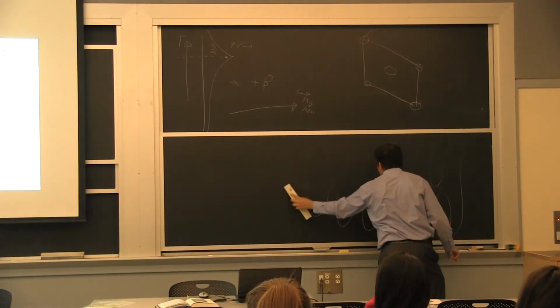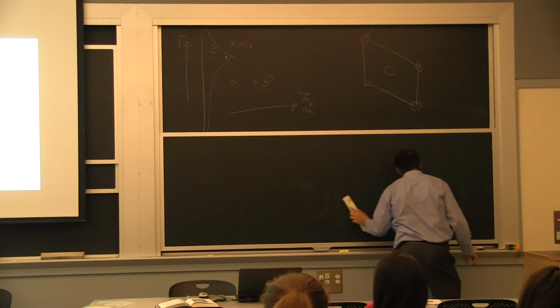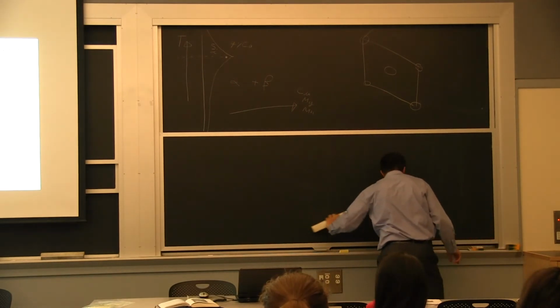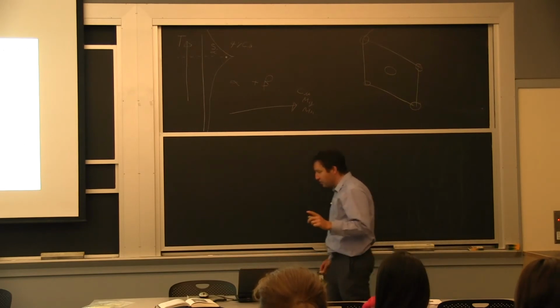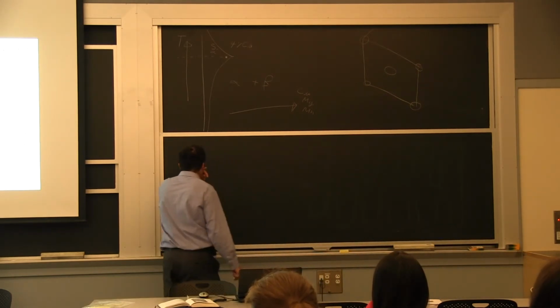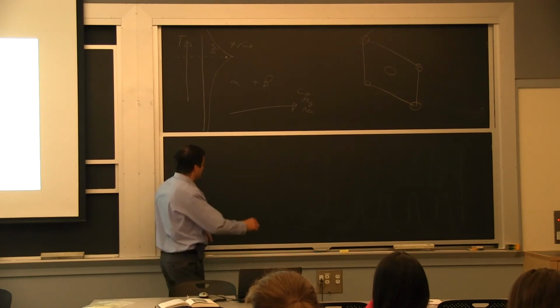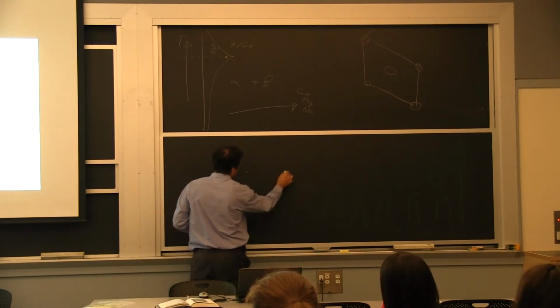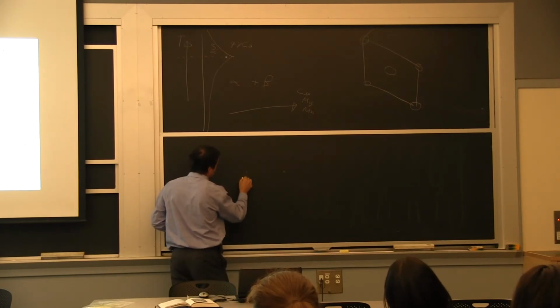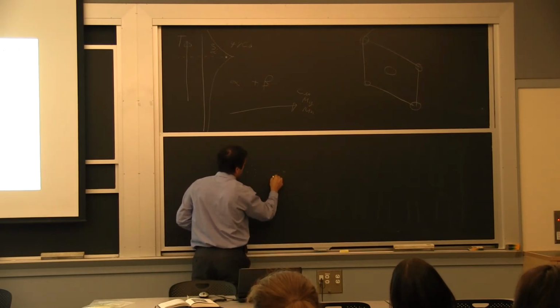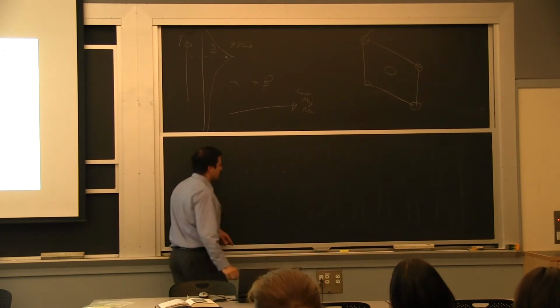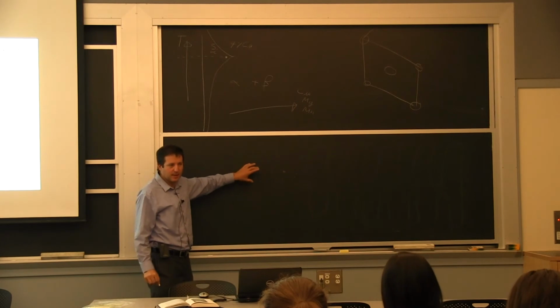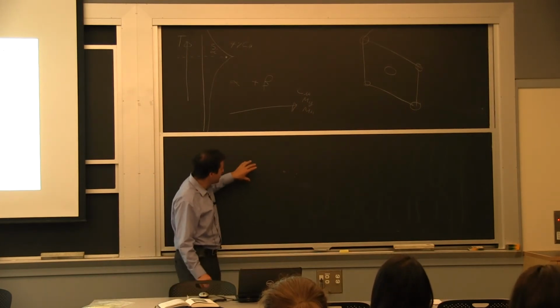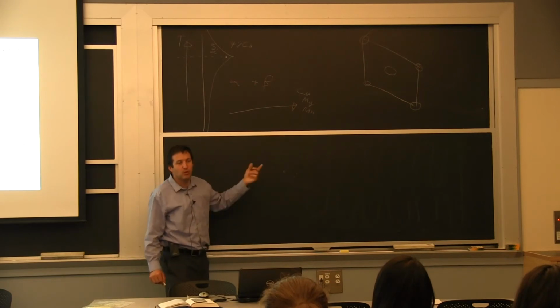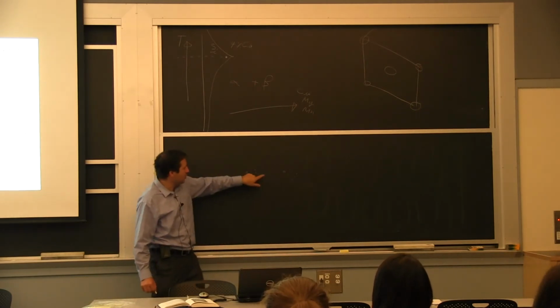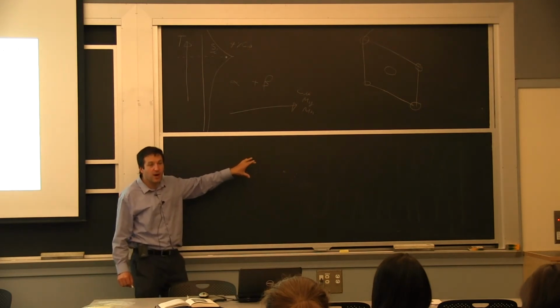I was able to form these precipitates that, for now, are just exactly what I wanted. They're not too small, so the dislocation doesn't just run right through them. They're not too big, so the dislocation doesn't just go around them. See, this is the precipitate. They form a certain strain field. Around the precipitate we call them semi-coherent, because there is an elastic strain, a deformation of the crystal in the whole volume surrounding the new phase that we created. So these are copper-rich precipitates. Around them we have a volume that's affected.